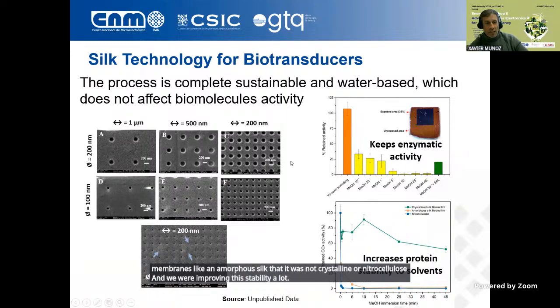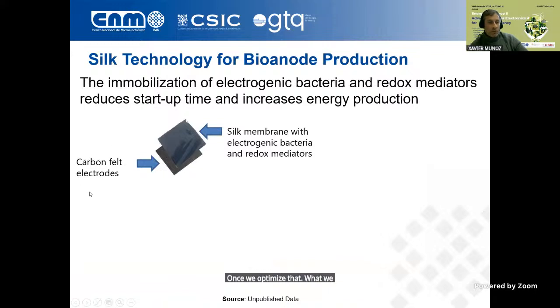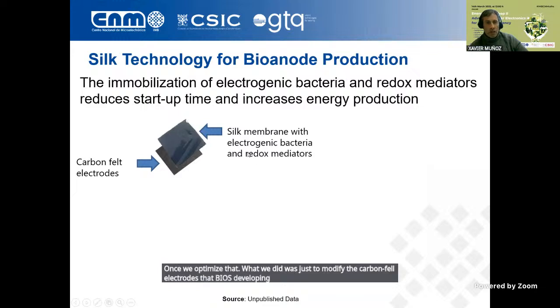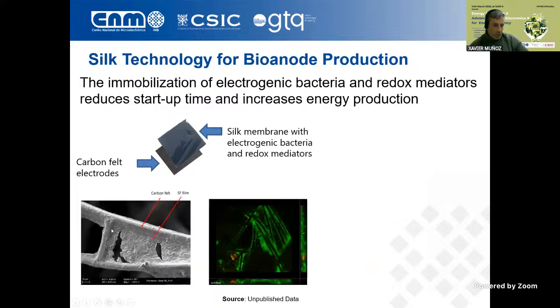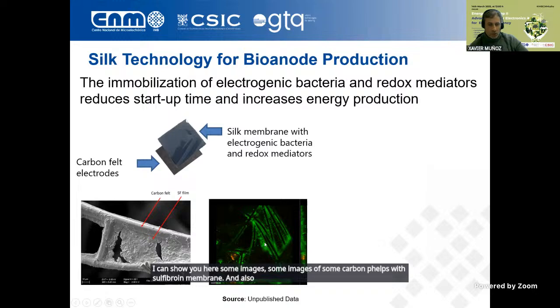Once we optimized that, what we did was just to modify the carbon felt electrodes that Bio was developing, and we incorporated in them electrogenic bacteria selected from the soil and also redox mediators in a way that we can induce the transference from the microorganism to the transducer, even if it is not electrogenic. I can show you here some images of these carbon felts with the silk fibroin membrane. And also here, this is an image to demonstrate that these bacteria that were immobilized following this protocol were still alive. They are green, they are alive.